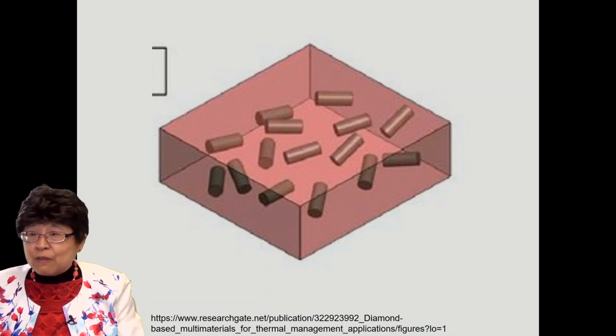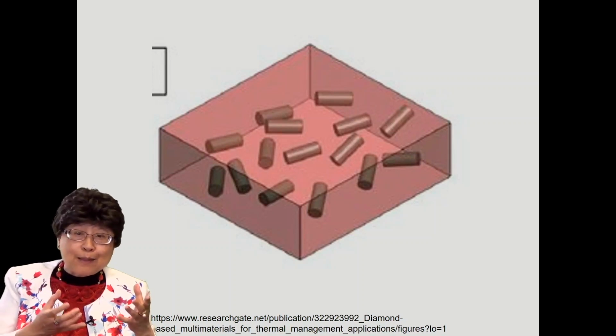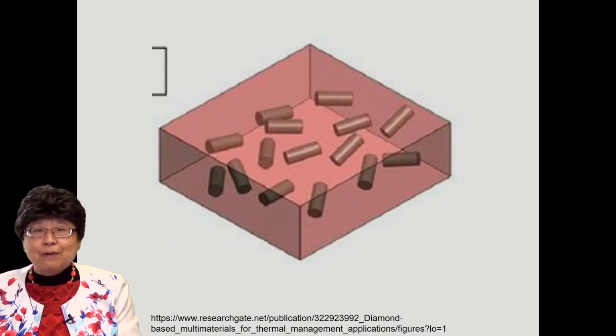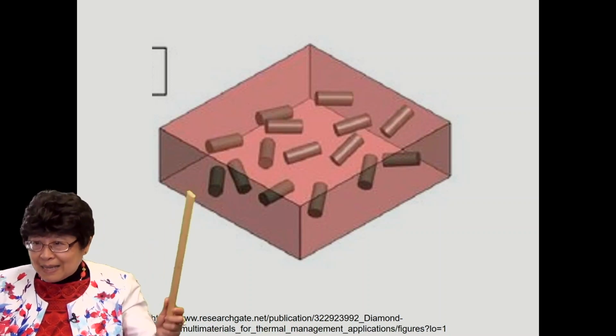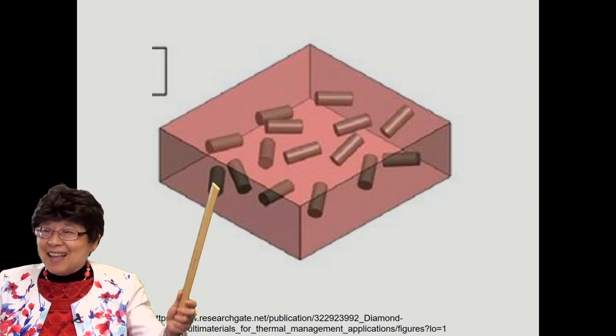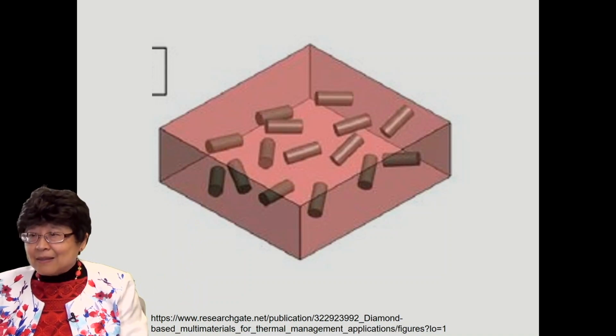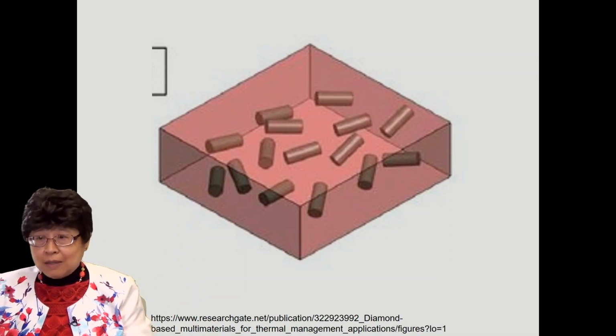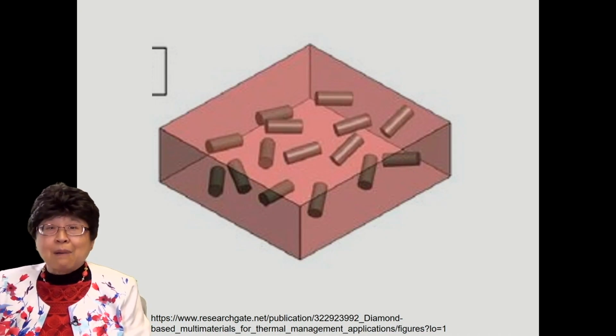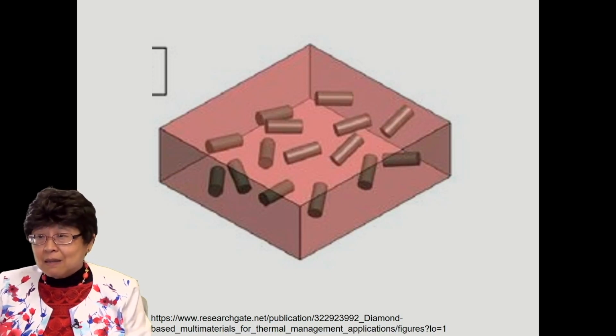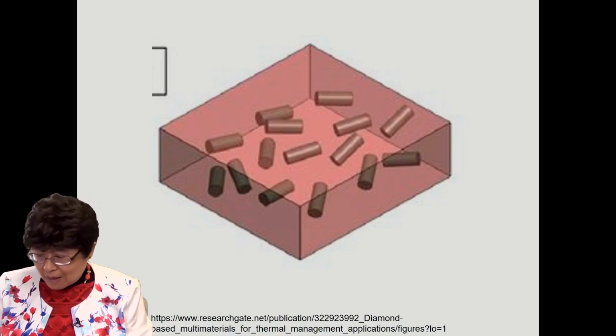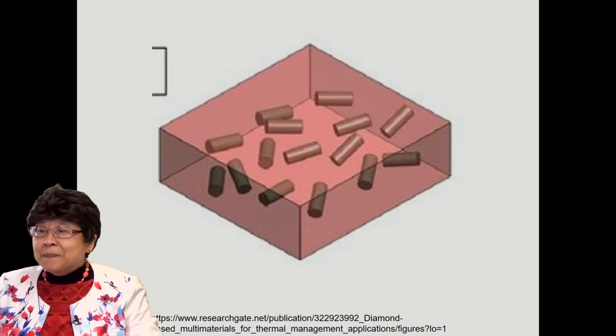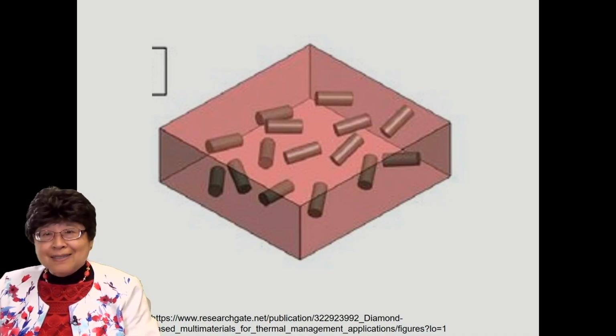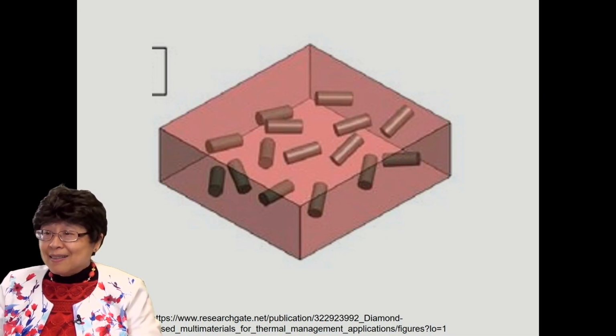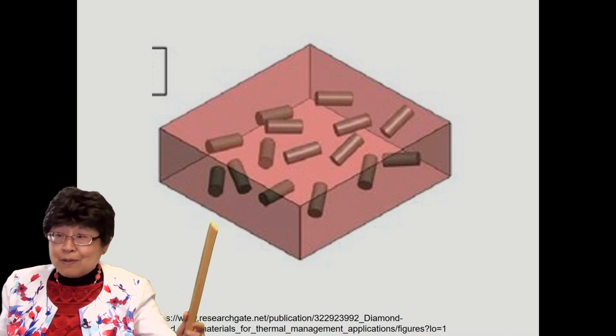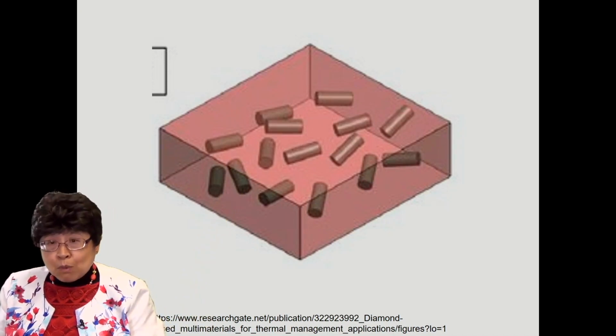So it would be much more effective if the filler is tiny, comparable to, say, the so-called skin depth, how much the radiation can penetrate. And so tiny fillers, nano size, would be very good. Having a lot of such interface area per unit volume would maximize the extent of interaction between the radiation and this filler, and so make the overall composite better in terms of the shielding effectiveness. And as the age of nanotechnology matures, the feasibility of using nano fillers to enhance the shielding effectiveness becomes more and more realized.